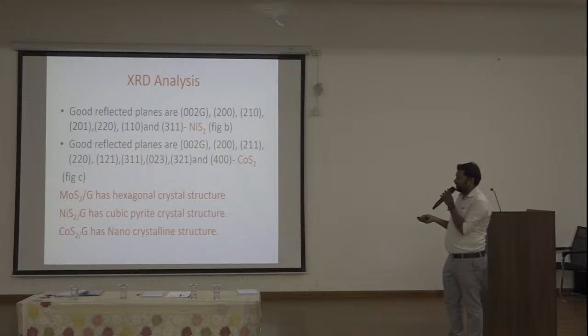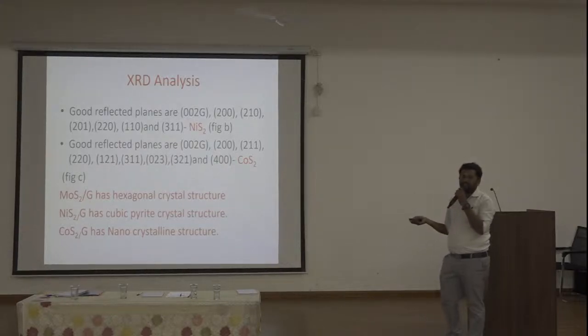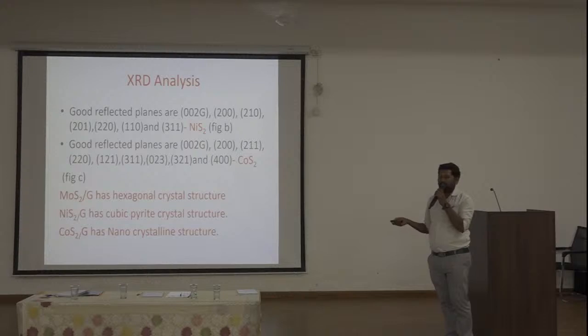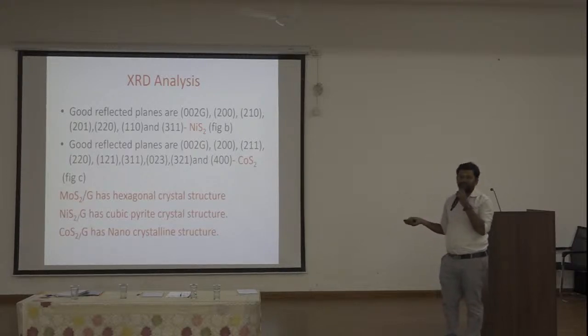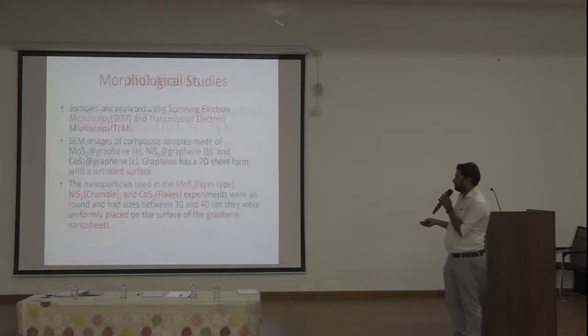So the XRD will reveal the various structures of the different materials. The first one, molybdenum disulfide with the graphene, has a hexagonal structure, the nickel disulfide with the graphene has a cubic pyrite crystal structure, and the cobalt disulfide with the graphene has a nanocrystalline structure. So these are the structures revealed by this analysis.